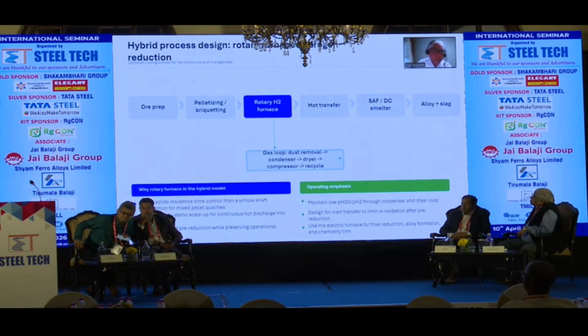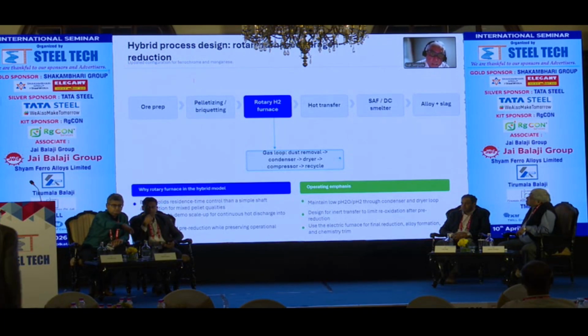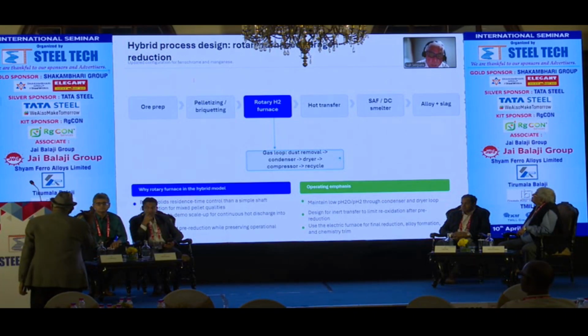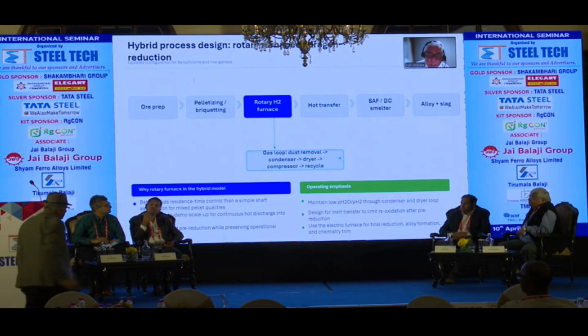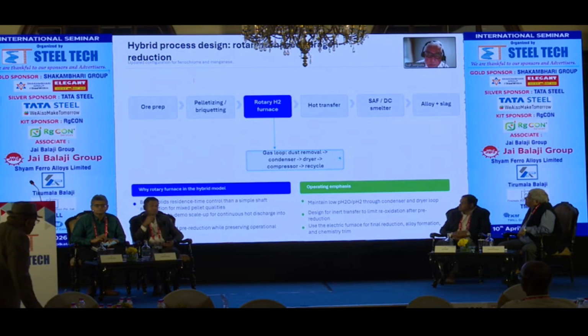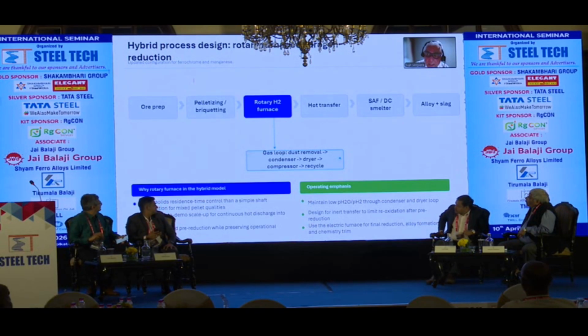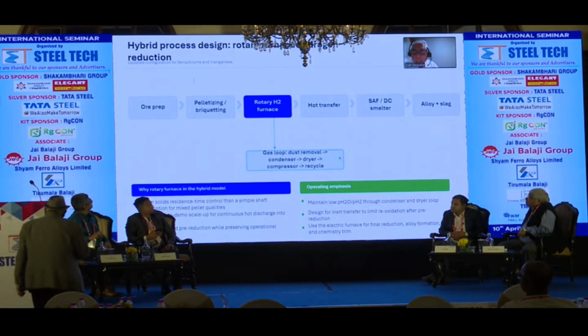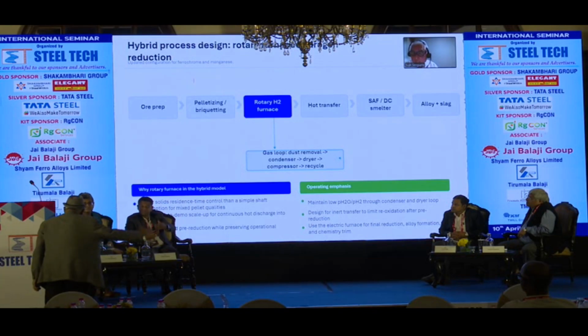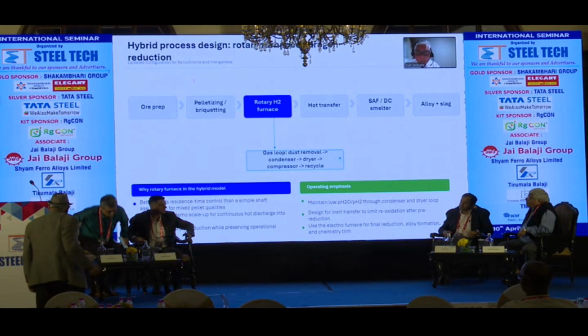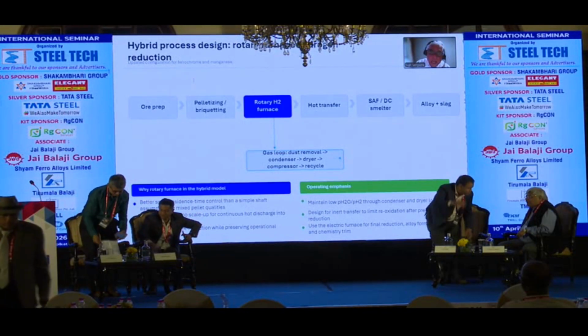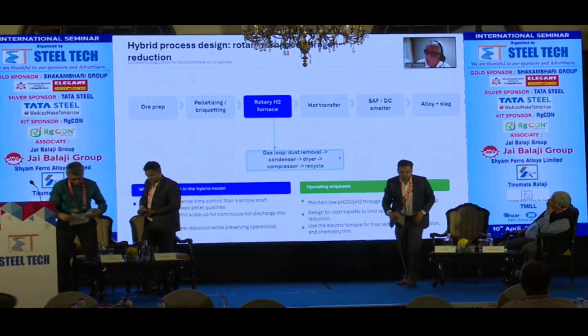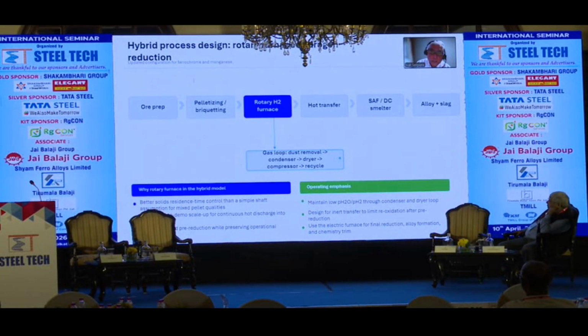So what is this? We have the ore prep, the pelletizing and briquetting, then we introduce this rotary furnace, then we do a hot transfer to the SAF and DC smelter furnace. Thinking aloud, hydrogen pre-reduction can reduce the energy consumption in the SAF or the DC smelter, and then there is recycling. If we introduce a carbon capture step, then the hydrogen itself and the CO itself could be fed back to the rotary furnace. This is a unique scheme that I have proposed, and if we do it, it could be one of the few in the world with this capability.